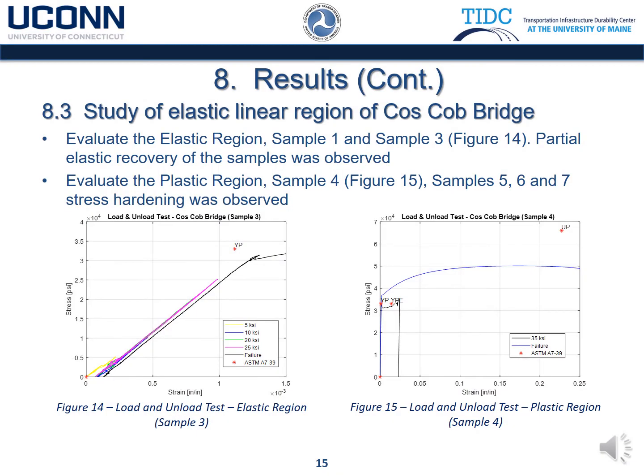Study of the elastic region of Cos Cob Bridge. Sample 1 and sample 3 were loaded and unloaded using different test rates and stress levels within the elastic region through failure. Figure 14 shows the stress-strain plot of sample 3, where we can see the load path for 5, 10, 20, 25 KSI and failure. Full elastic recovery was observed in sample 1 and sample 3.